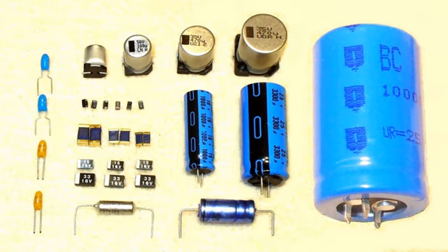However, solid polymer electrolytic capacitors, aluminum as well as tantalum and niobium electrolytic capacitors also have a lifetime specification. The polymer electrolyte has a small deterioration of conductivity caused by a thermal degradation mechanism in the conductive polymer. The electrical conductivity decreases as a function of time, in agreement with a granular metal-type structure, in which aging is due to the shrinking of the conductive polymer grains. The lifetime of polymer electrolytic capacitors is specified in terms similar to non-solid e-caps, but its lifetime calculation follows other rules, leading to much longer operational lifetimes.